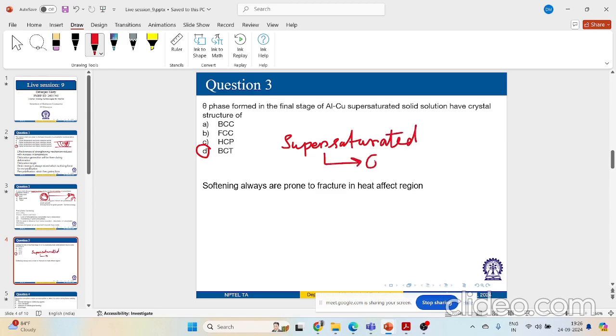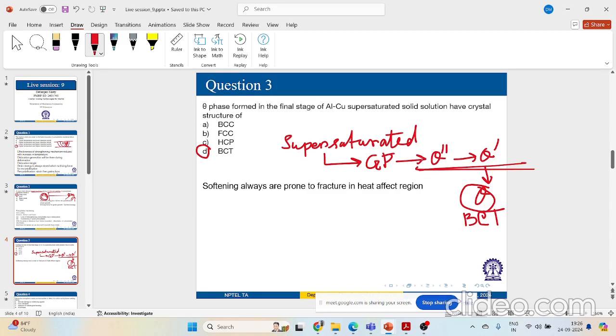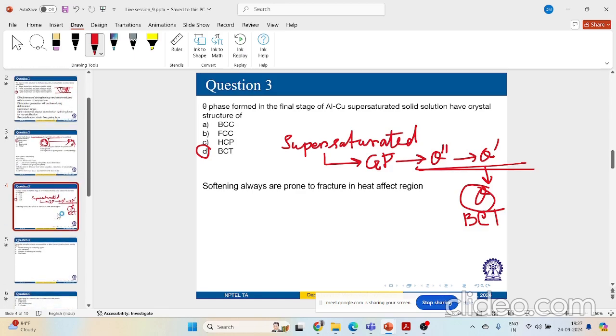From there you will be forming the GP zone, then theta double dash, then theta dash, and finally theta, which is your equilibrium phase. So this is a BCT structure. The other crystal lattice structures can be coherent or semi-coherent with the structure of the solid solution. Fine.